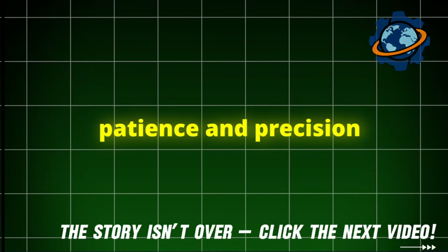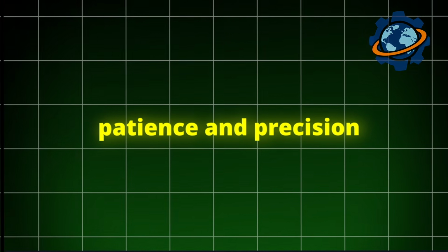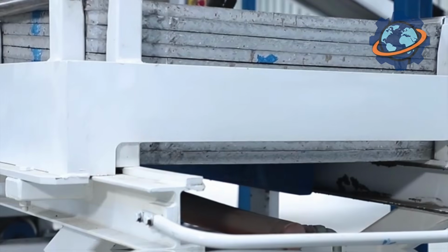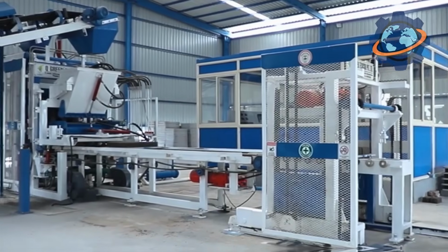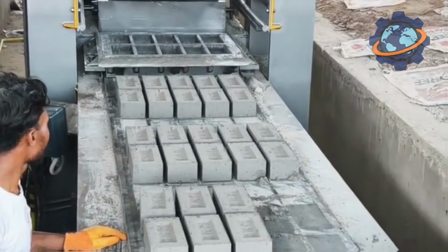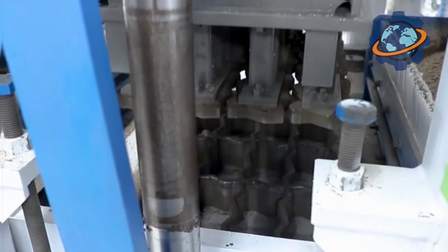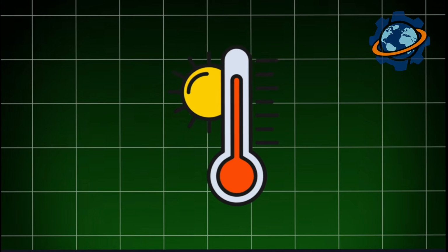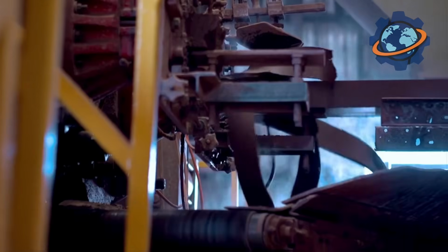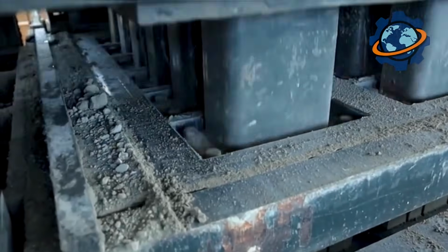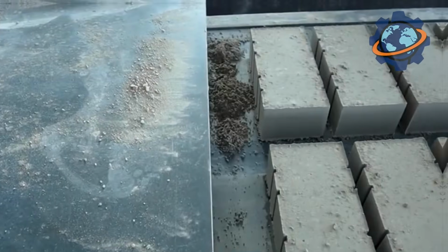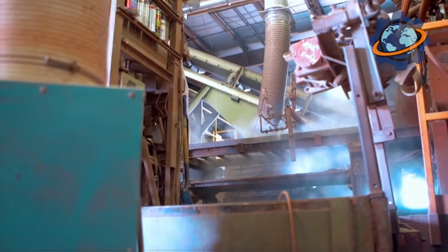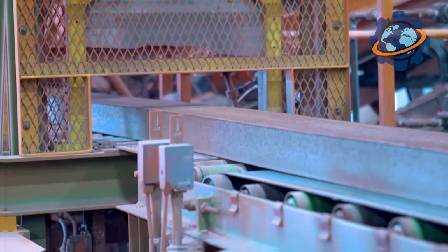The next stage requires not strength, but patience and precision. The green bricks are carefully placed on kiln cars and sent to long tunnel dryers. This is a slow and delicate stage, which can last from 1 to several days. Inside the dryer, a carefully controlled microclimate is maintained. The temperature is gradually increased, and the humidity is reduced. It is important that the moisture leaves the brick as evenly as possible from its entire thickness. Any rush or violation of the regime will lead to the outer layers drying faster than the inner ones, which will create critical internal stresses and simply tear the brick apart with cracks from the inside.